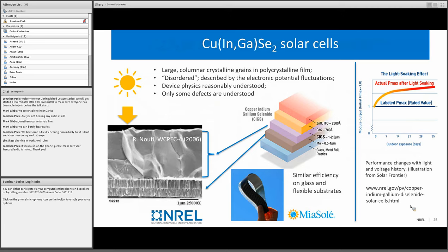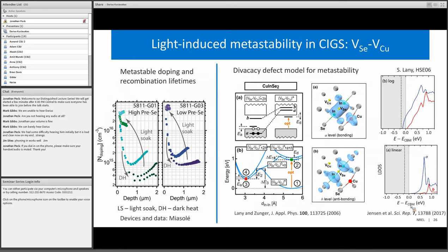So we did this research in collaboration with researchers at NREL as well as researchers at MiaSolé. The NREL CIGS is grown in a three-stage process on glass substrates. They are beautiful grains. The CIGS solar cells grown at MiaSolé are grown on flexible steel substrates to enable different applications. The data on the left is from MiaSolé, where the capacitance voltage shows what happens during the light soaking and then dark heat treatment, in that the carrier density changes by close to an order of magnitude. And that is one of the manifestations of this metastability, which is reversible. And the devices can be cycled many times from the lower doped and higher doped state.